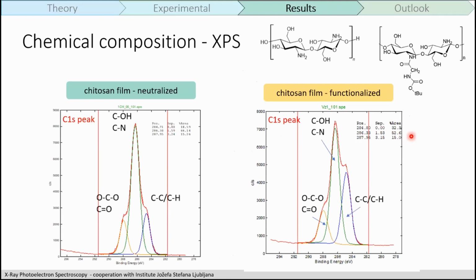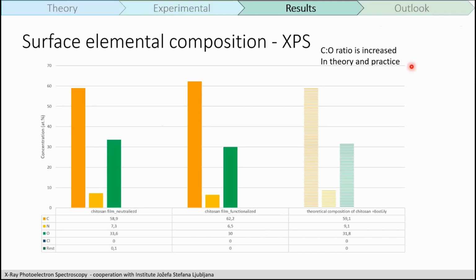To confirm that, we then measured XPS. From the carbon-carbon bonds of the neutralized film compared to the carbon-carbon bonds of the functionalized film, you can see that the area has risen from 18% to 33%, which once again points toward the formation or binding of this Boc-glycine protective amino acid on the surface of our film. This was also confirmed with the surface elemental composition, where the ratio is increased for the actual measurements as well as for the theoretical composition that we calculated.